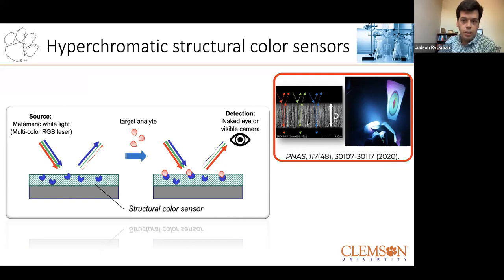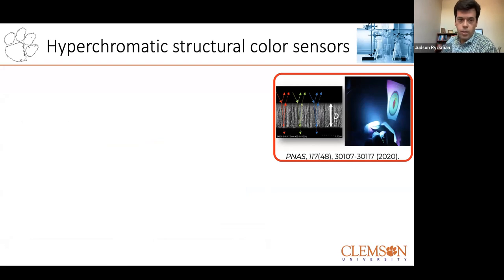So physically what happens here, and it is important to note that porous silicon, because the pore diameter, let's say 30 nanometers, is much, much smaller than the wavelength of, say, visible light, say 500 nanometers, it acts as an effective medium. So we have a refractive index that's between that of silicon and air. And as you add more molecules inside, the refractive index goes up and the optical spectrum will change. So the idea here is to make a sensor that can be read by a camera or even by, say, the naked eye. So how do we do this?